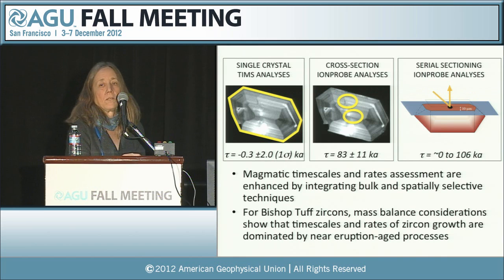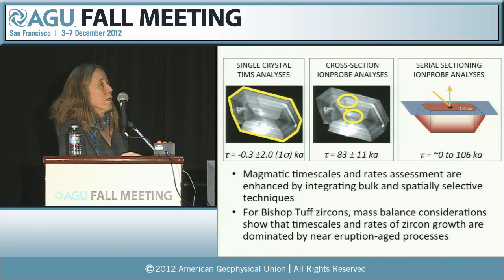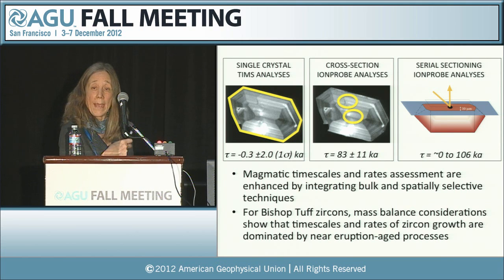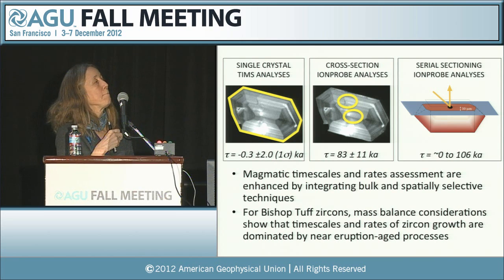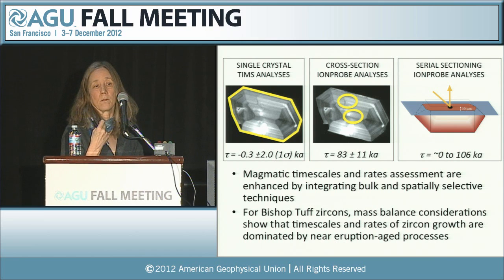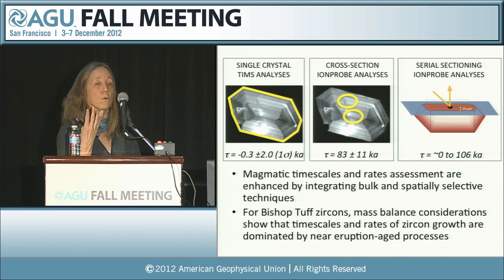The tau that we get when we do our kind of averaging over a cross-section, and then this range of different taus that we got that were sequential as we went into the crystals. And again, I really want to emphasize, I really think these approaches are complementary, not contradictory. And what they're really telling us in this case, and I think there are further things that we can take out of this, is that based on the mass balance consideration, most of the crystal growth has occurred relatively recently before the eruption. And that there are some relic old cores within the crystals that may have been either antecrysts or just early evidence for the onset of this magma chamber.